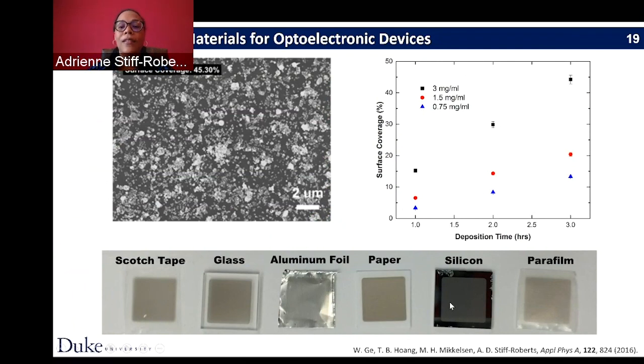And this is showing that we deposited these silver nanoparticle films on a variety of substrates. And so the wetting properties would be very different on each of these substrates. If this were not a dry process, you wouldn't see this similar type of deposition regardless of the substrate. So this is nice evidence that we essentially have a dry process with this.